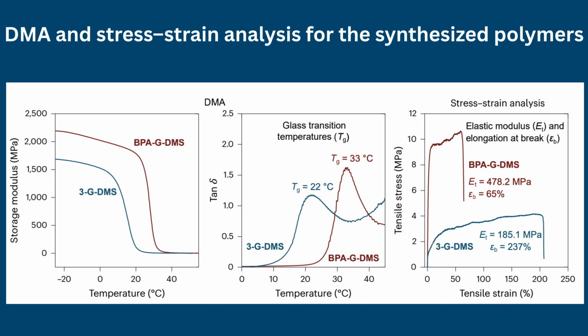Thermal properties. Dynamic mechanical analysis and differential scanning calorimetry indicated that the BGF-based polyester has a lower glass transition temperature, Tg approximately 22 degrees Celsius, compared to the BPA analog, Tg approximately 33 degrees Celsius. This reduction reflects increased chain mobility and flexibility.